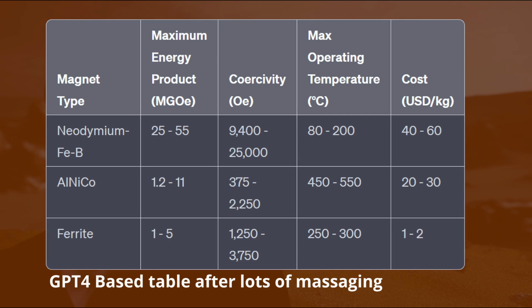The first line shows neodymium-based magnets as a reference for comparing the other metals. The other two lines show alnico, or aluminum nickel cobalt magnets, and ferrite magnets, made of ceramic materials and iron oxide, which is a fancy way to say rust. Looking at the maximum energy product, we see that at 25 to 55 MGOE, neodymium trumps alnico's 1 to 11 and ferrite's 1 to 5.